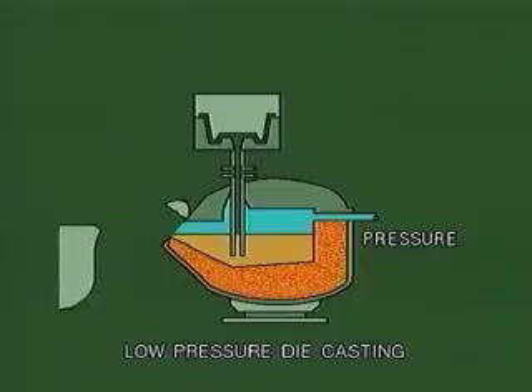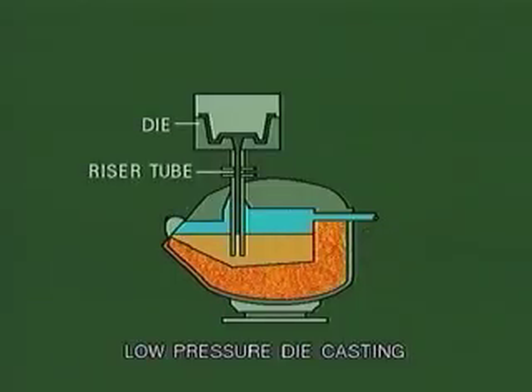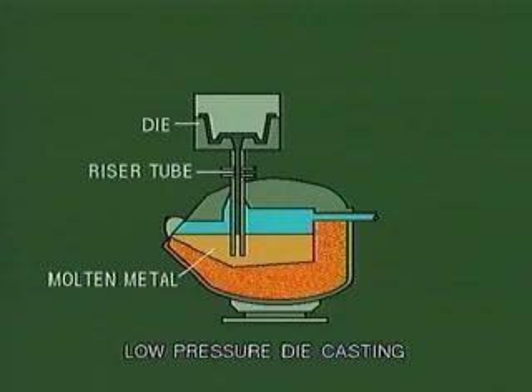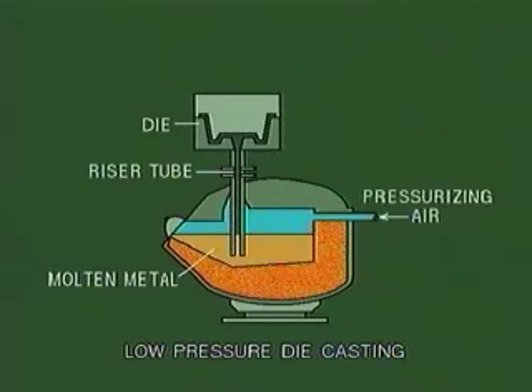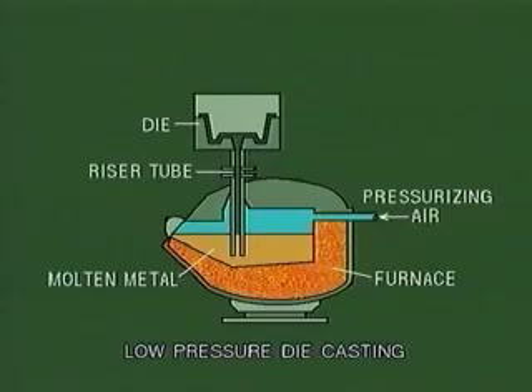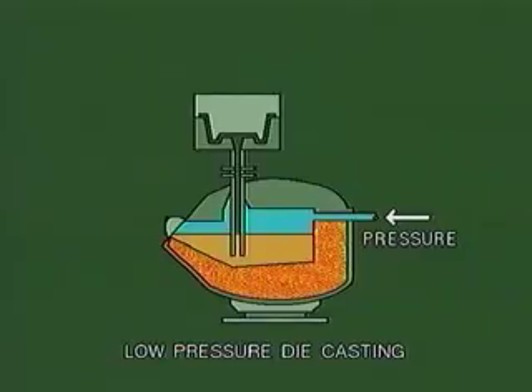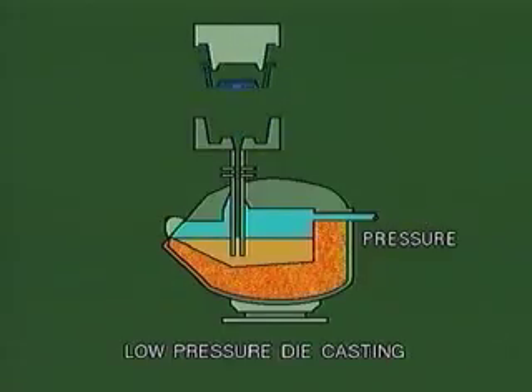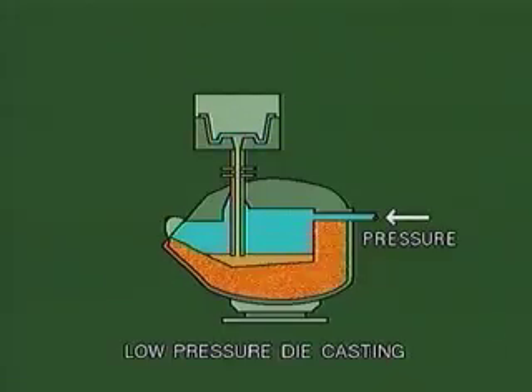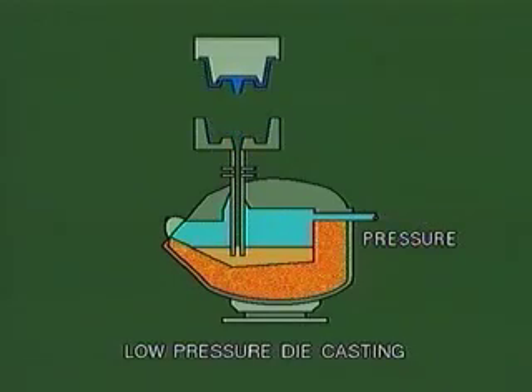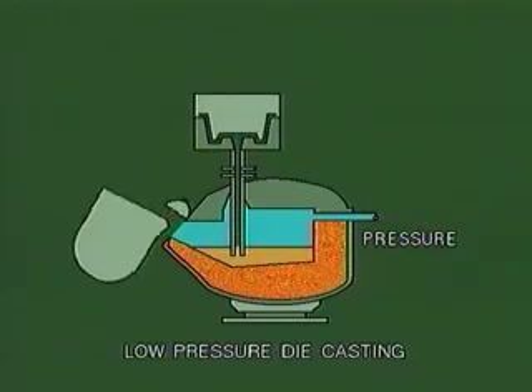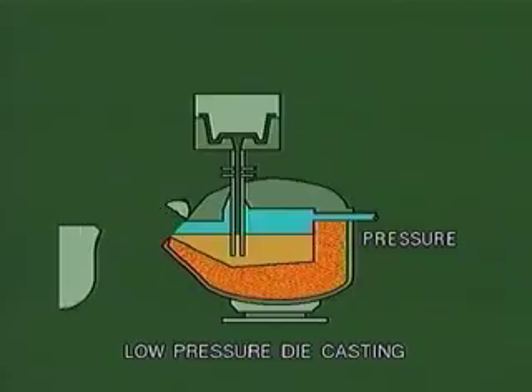The low-pressure die casting machine is made up of a die, a riser tube, a crucible that can hold 700 kilograms of molten metal, a pressurizing system, and a heater to maintain the metal at an exact temperature. When low air pressure of several hundred kilopascals is applied, the metal is forced up the tube, gently fills the die and solidifies. The pressure is then released, and the liquid metal in the riser tube returns to the crucible. After about 40 castings have been produced, a hatch in the base of the low-pressure die casting machine is opened and the crucible is refilled. The process then recommences.